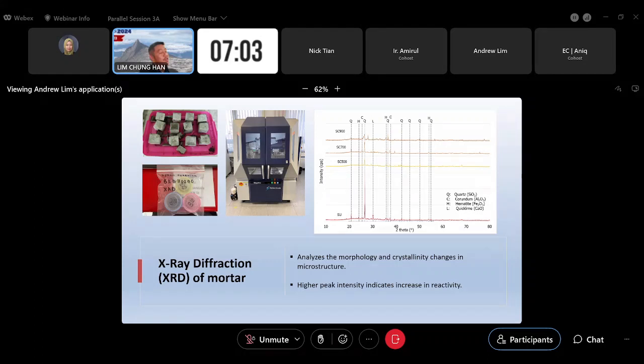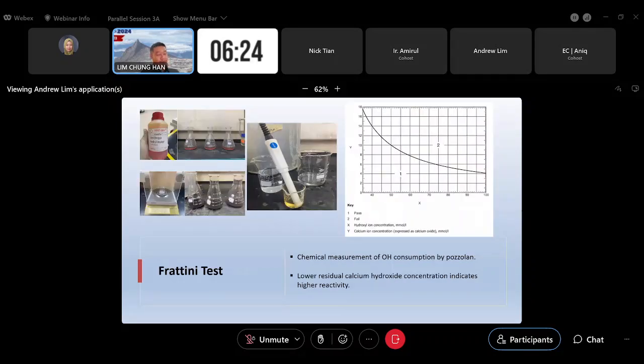Basically, for this test we also cast our mortar samples, and then we take a small chunk out of the mortar sample, crush it, and put it in this machine to generate the XRD diffractogram, which will tell us how crystalline the material is. We will relate the crystallinity with the reactivity. So in essence, the higher the intensity, it should reflect higher reactivity as well, at least.